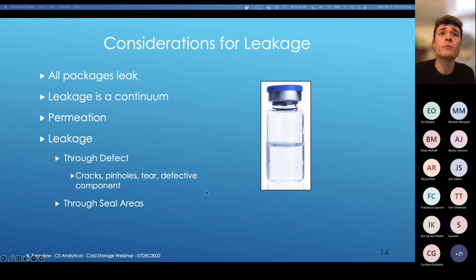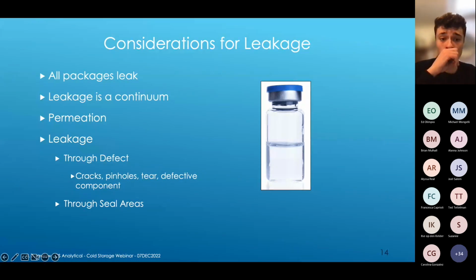Leakage, however, is typically through one of two areas. Leakage really can stem from two different areas. We can have leakage literally as a result of a defect, through a crack, a pinhole, a tear, a defective component that's not creating that seal. But also we can have leakage through actual seal areas themselves.